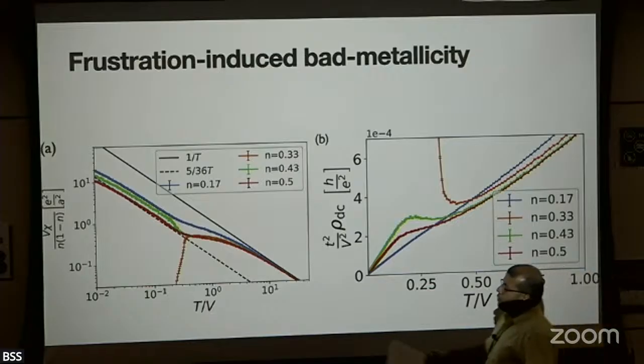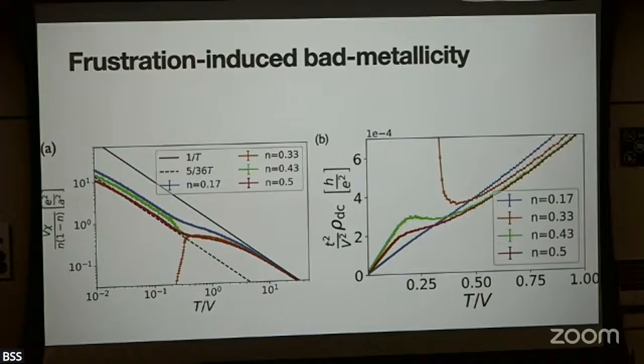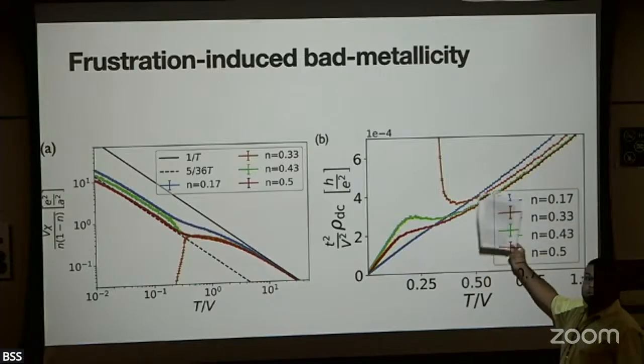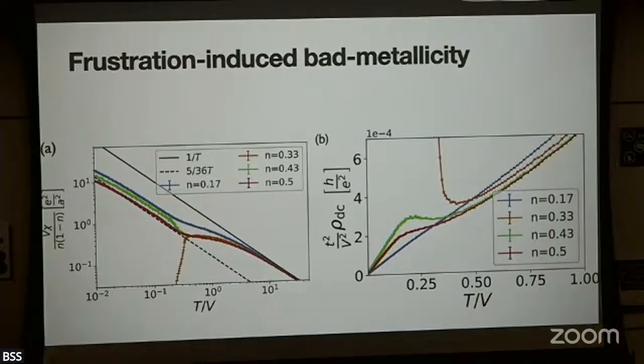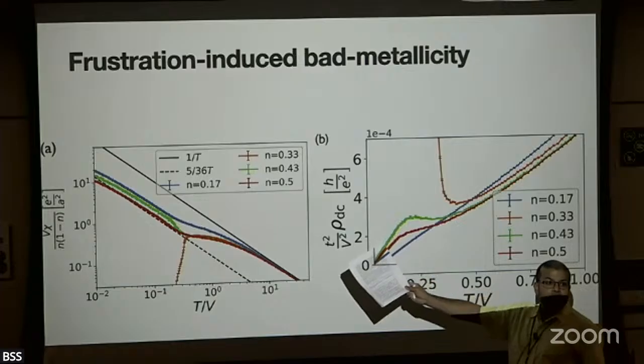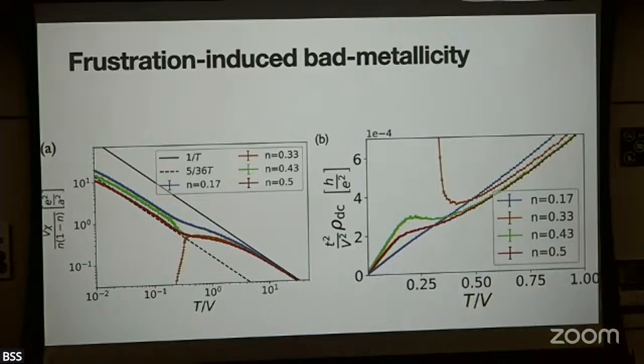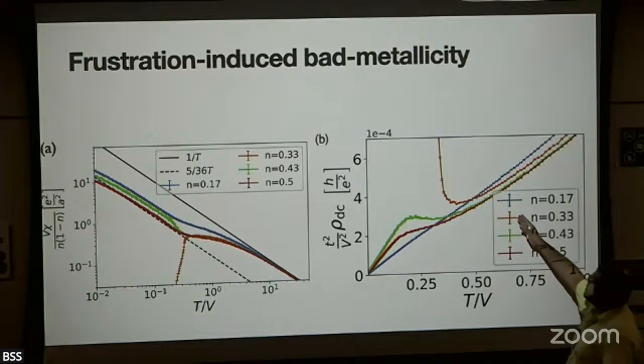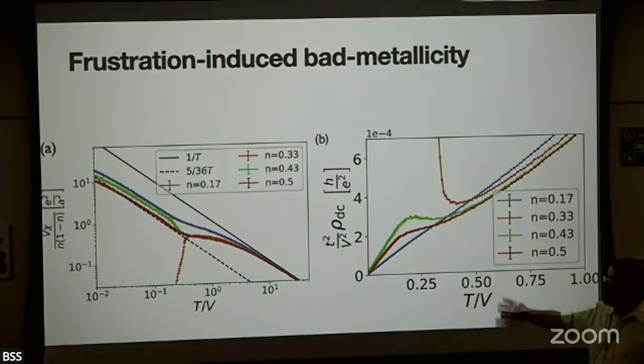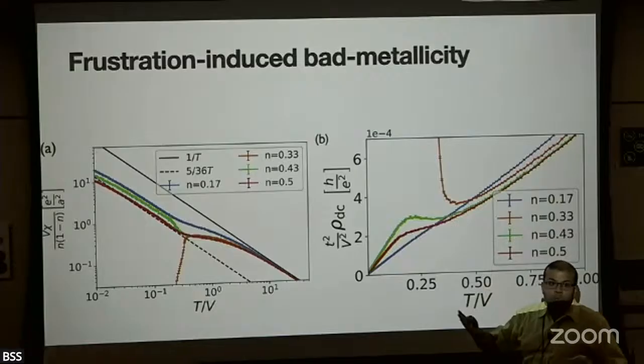Okay, now if you calculate the conductivity, just by evaluating this sum using Monte Carlo, you see all kinds of interesting behavior. Importantly, you do see different kinds of regimes of T-linear resistivity, which are controlled by the compressibilities in the two different regimes, okay? But if you look at it closely, as you're varying the filling, there exists some intermediate region where you would have thought they would be very distinct slopes. They're not. They're smoothly connected. There's nothing profound about this, but it's just that, when you're looking at the finite temperature properties, you can have smooth crossovers, and there might be some intermediate regime where the slopes just line up.